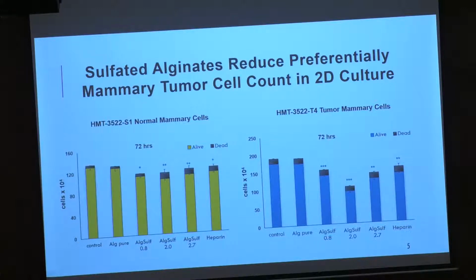We grew these cells in a monolayer, and then we added sulfated alginates on them, and we counted the number of viable cells and dead cells. As you can see, alginate sulfate 2.0 had the most potent effect when we compare it to the untreated control or to the pure alginate that is not sulfated. The effect was more potent in the T4 cells, as the number of viable cells decreased by half.